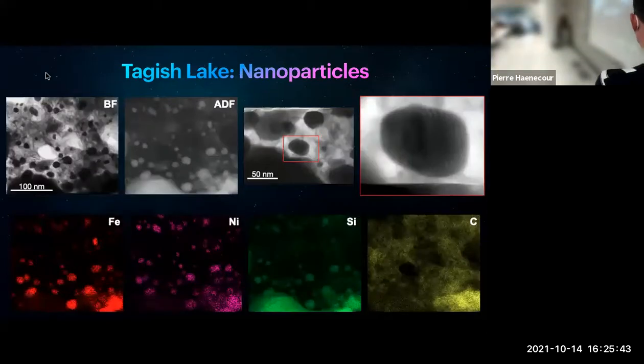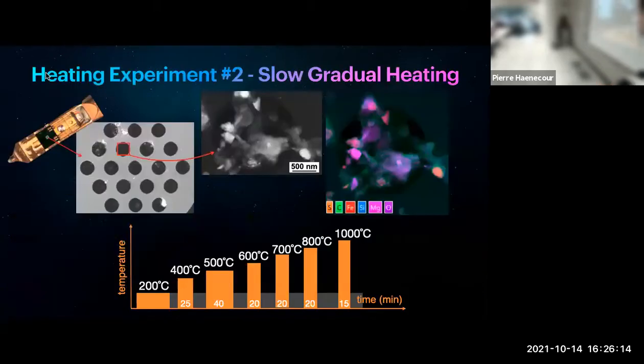And then just to show you the same idea, that those nanoparticles are all around, they are colored for iron, nickel, and then a little bit of silicon, showing you that they are iron nickel particles with a little bit of silicon. And it's difficult to see on this screen, but the nanoparticles are even more complicated. In this particular one, you can actually see exsolution. So it's not a homogeneous decomposition. There is a lot of complicated things happening to the sample as it's being heated.